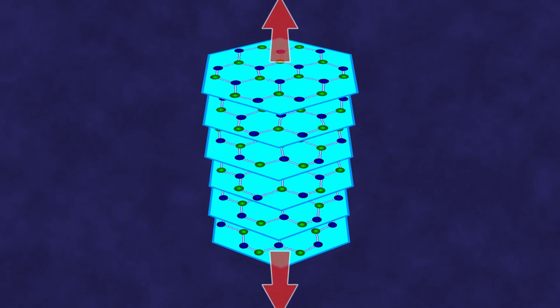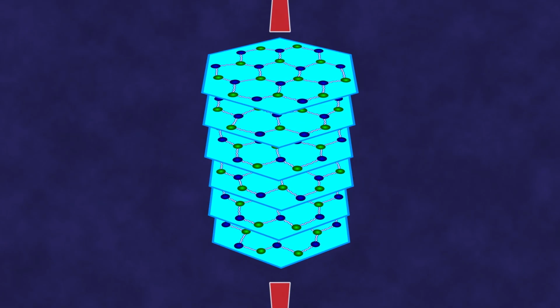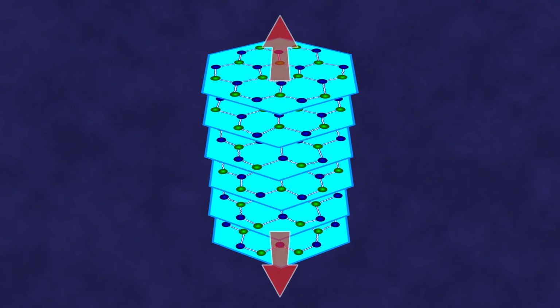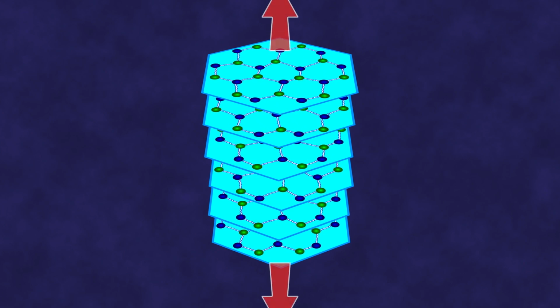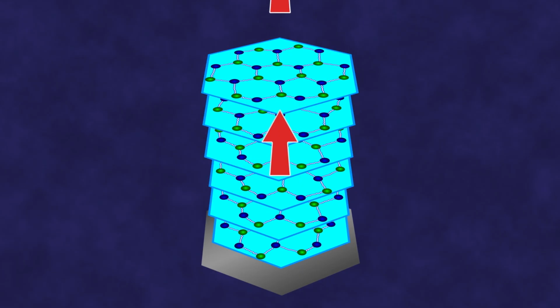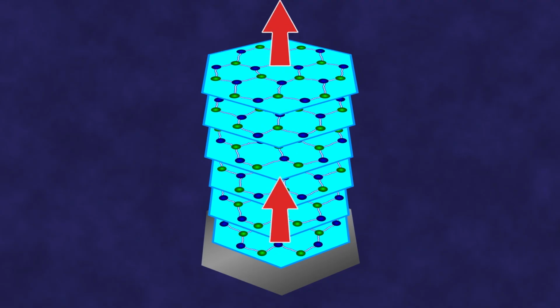So the ions in flakes of hexagonal boron nitride do not just oscillate at a certain preferred frequency, like the ions in barium sulfate crystals. They also oscillate in a certain preferred direction. The result is a kind of double selectivity, by frequency and by direction of emission. And while in the case of barium sulfate, only about 1/6 of the total radiation escapes into space, in the case of hexagonal boron nitride, this fraction increases to 50 to 60%. And if the barium sulfate particles are backed with a layer of metal that has a high reflectivity for electromagnetic radiation, the efficiency can rise to nearly 100%.